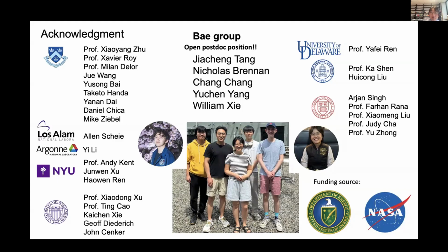Yeah, so I think the CrBr3 and CrCl3 are very similar to the triiodide system that I talked about. If you were to try the same measurement, you essentially would not see the effect that I discussed, because the exciton is so localized. Essentially, they don't care what the spin environment around it is.